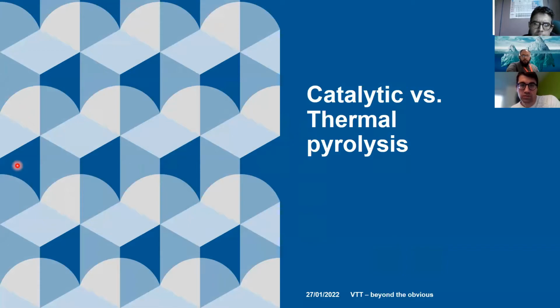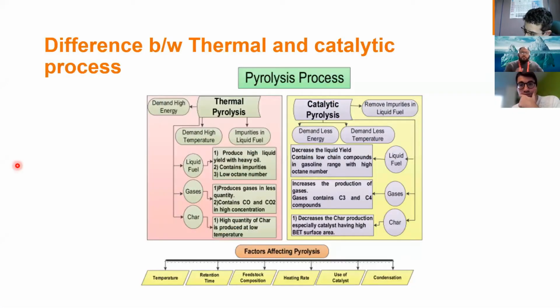Then I will jump to catalytic pyrolysis and try to say what is the difference between a catalytic pyrolysis and a thermal pyrolysis. If you look at this picture, there is a comparison of the thermal pyrolysis and catalytic pyrolysis. So in the thermal pyrolysis, there is more energy demand. So basically, if you need to pyrolyze some plastic mixture and it needs 600 Celsius for the degradation in a thermal pyrolysis, it could mean that in a catalytic pyrolysis, it needs 500 because of the use of the catalyst. Catalyst lowers the activation energy or the degradation onset. So there's higher demand of energy in a thermal pyrolysis, which means actually high temperature requirements. And there can also be impurities in the liquid fuel in the thermal pyrolysis if there are impurities in the feedstock.